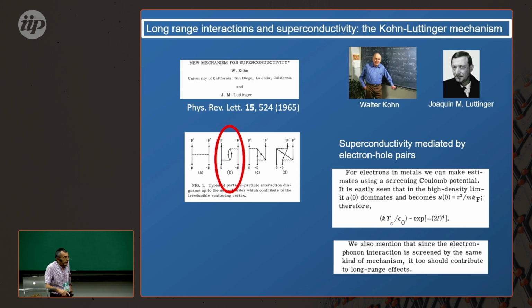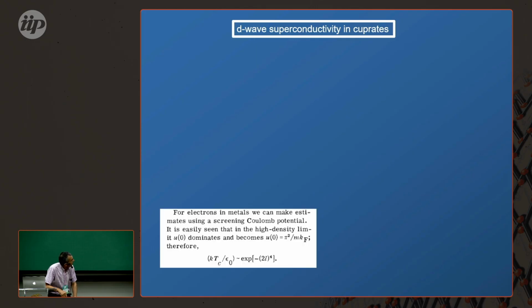Let me emphasize, they also said that if you screen the interactions, highlighted inside the red ellipse, using a long-range interaction screened with an RPA-like bubble, you have to take into account longitudinal acoustic phonons as well, because they couple to the same electron-hole pairs, the same charge fluctuations included in an RPA calculation.